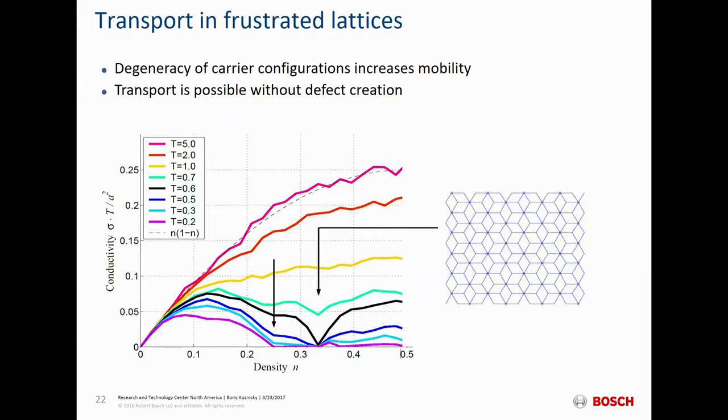In fact, in this triangular model, Gregory Wannier showed, before he got into Wannier functions, explicitly that a triangular antiferromagnetic Ising lattice cannot freeze at any finite temperature because of the frustration. So this is a suppression of phase transition that allows the system to keep some degree of freedom even at zero temperature. When you turn on long-range interactions, that's no longer true, but it's still true that the system will transport charge much more easily where you have this degree of degeneracy and frustration.